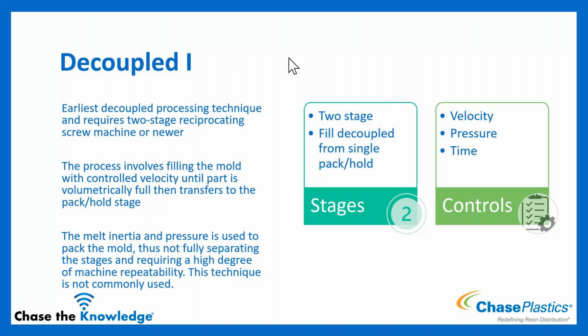This is the earliest adaptation of it, and it requires a 2-stage reciprocating screw machine or newer to accomplish. In this process now, we are filling the mold with a controlled velocity until the part is volumetrically full, and then we transfer to the pack and hold. In this scenario, the melt inertia from fill and the pressure generated is used to pack the mold. It's not a fully separated decoupled process where the fill and pack are handled completely separately, but it's more the first acknowledgement that the packing of the mold was also a critical portion of the cycle. So this is a two-stage process, and fill is decoupled from a single pack hold combined step. And now you have a velocity, a pressure, and a time as your control variables.